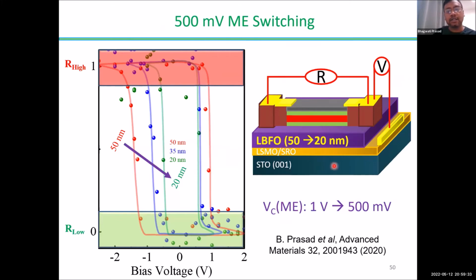It's not as simple as it looks here, because you also have to look at how the interface engineering, pinning effects, and other things are happening, whether you still have a magnetoelectric coupling when you reduce the film thickness. So it requires a lot of optimization. With that, we reduced the magnetoelectric switching voltage all the way down to 500 millivolt.